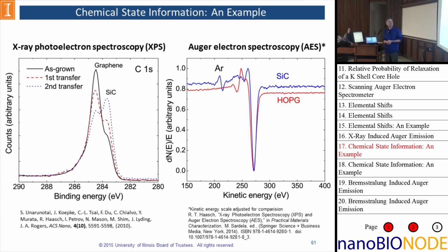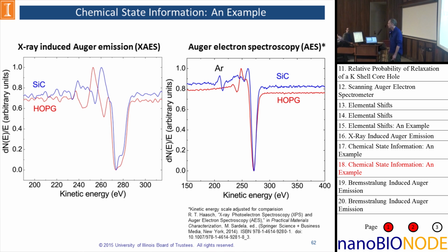Here's an example of silicon carbide with highly ordered pyrolytic graphite. Besides the peak energy shift, I adjusted the kinetic energy scale of these lines just for comparison. I overlapped the two. So besides the energy shift of this line, there's a little bit of change in the shape of the pre-peak. And you use that then to differentiate HOPG from SiC. Again, this is a comparison of that same line, the same set of data collected with the X-ray source instead. A little bit extra detail you can see on the X-ray induced Auger spectra.